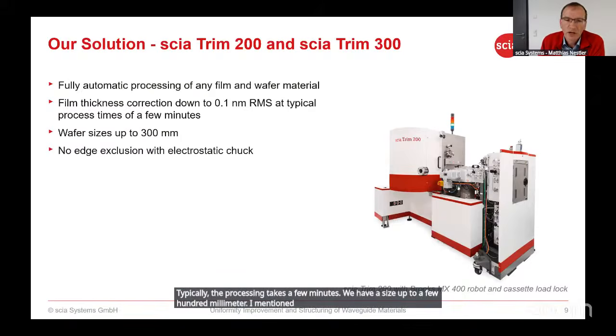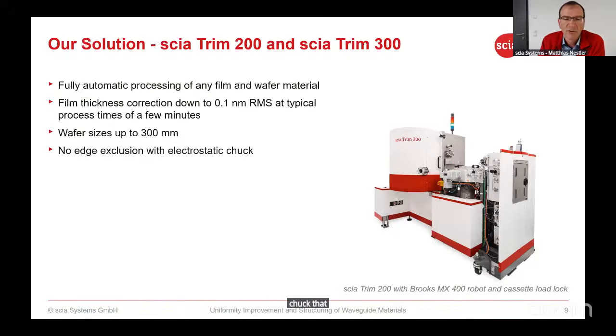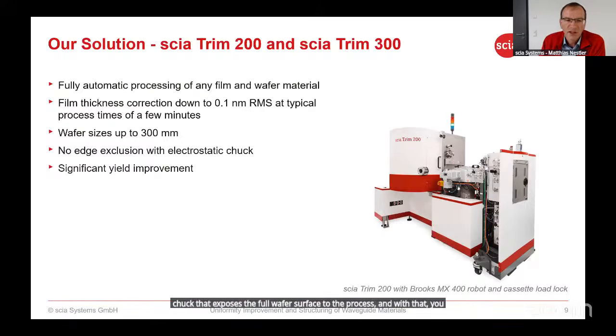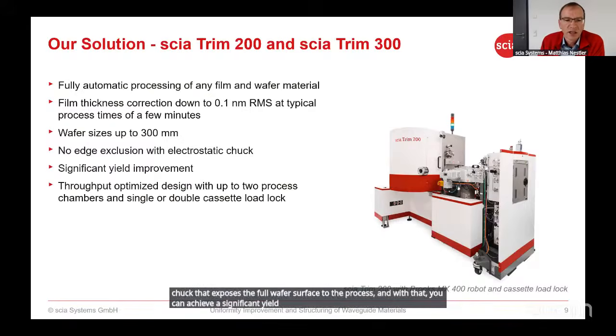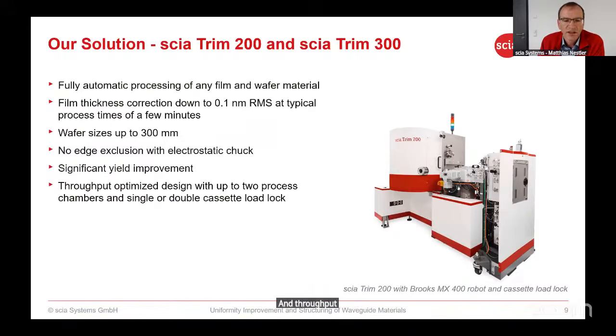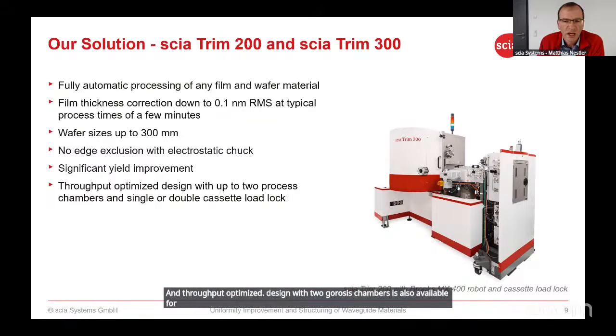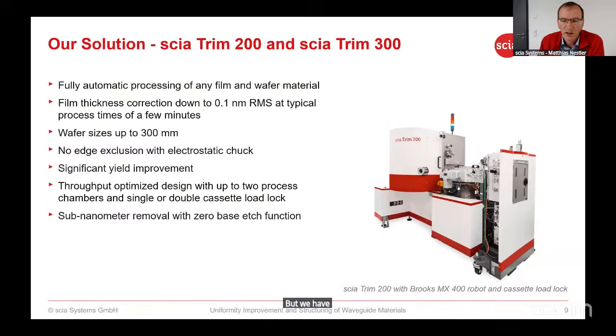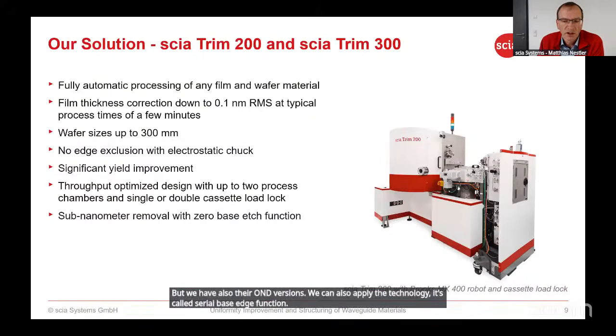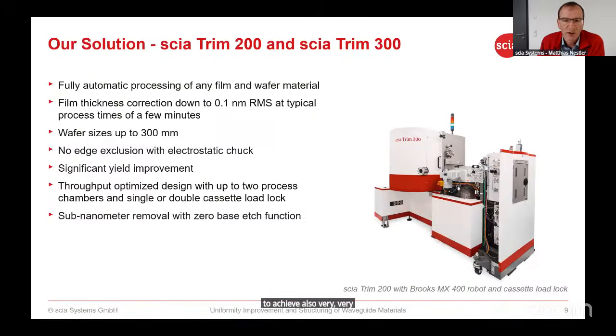I mentioned already no edge exclusion since we have an electrostatic chuck that exposes the full wafer surface to the process. And with that, you can achieve a significant yield improvement, and a throughput optimized design with two process chambers is also available for high throughput manufacturing demands. But we have also the R&D versions. We can also apply their technology, called zero base etch function, to achieve also very, very low corrections with high precision.